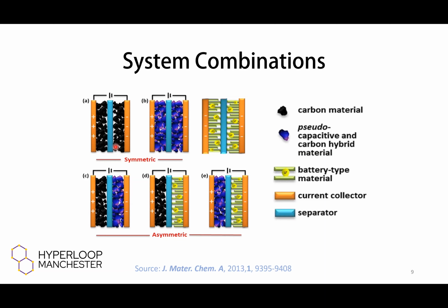So, for example, because the supercapacitor system is purely physical, the charge storage mechanism is very quick and very fast, so they become very powerful devices. But in the battery type material, the charge storage mechanism requires a chemical reaction, which takes time, and it can be quite slow. It takes time for materials to travel deeper into the material structure. So by combining them together, you can create hybrid devices, which are more powerful and higher energy density. So you get interesting stuff out of that.